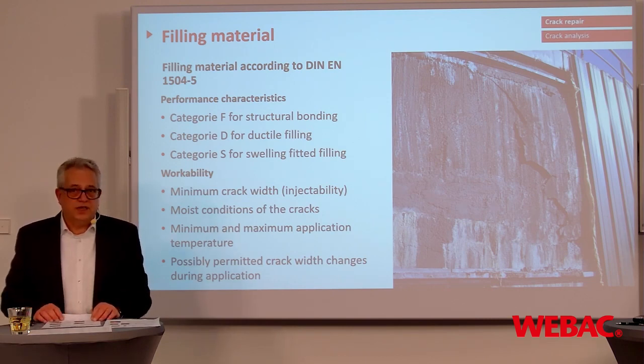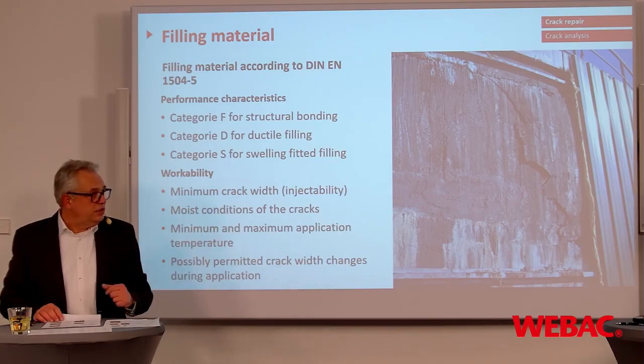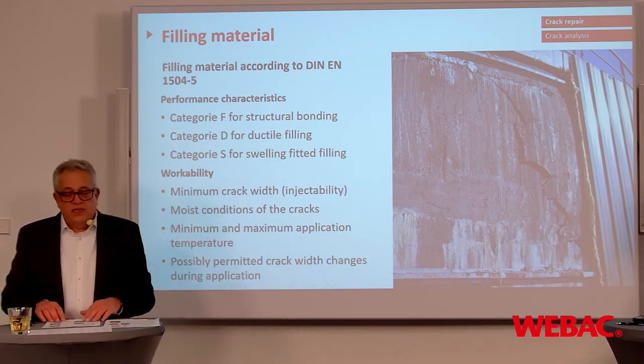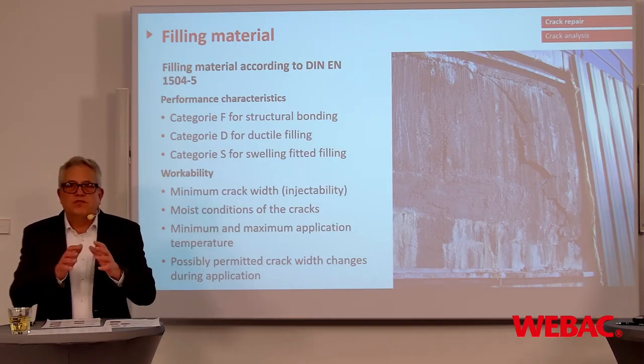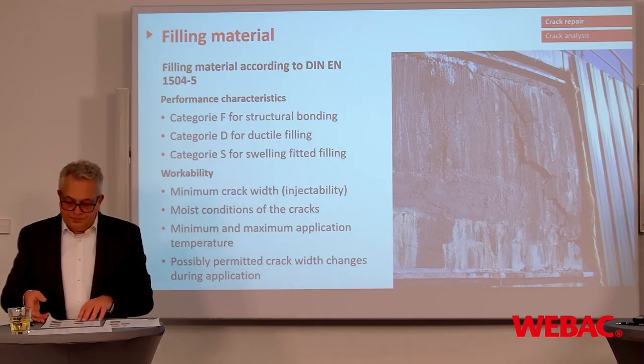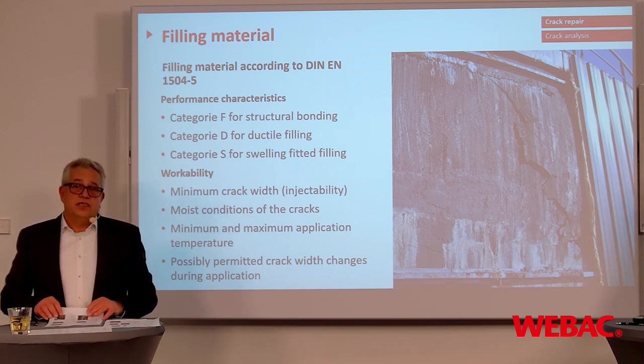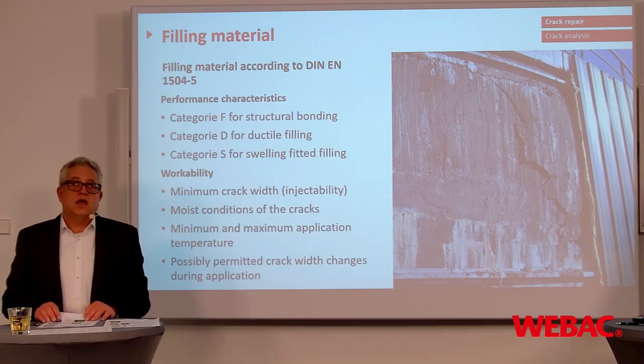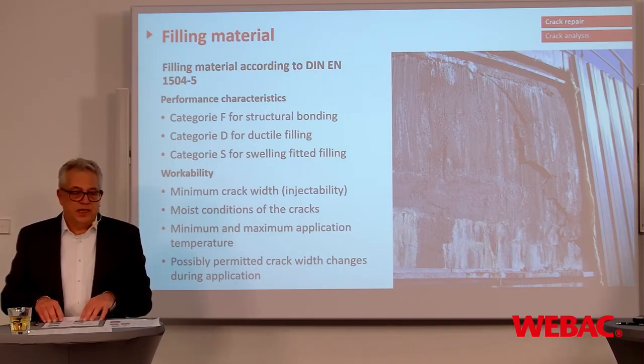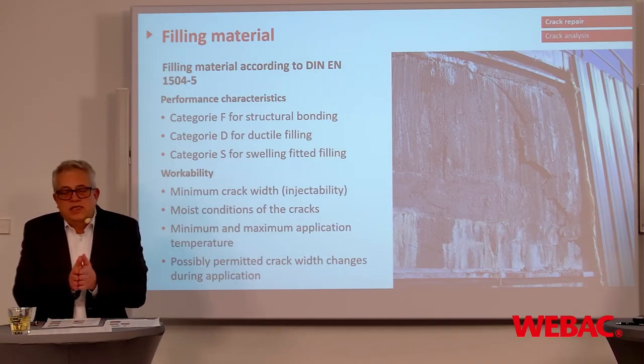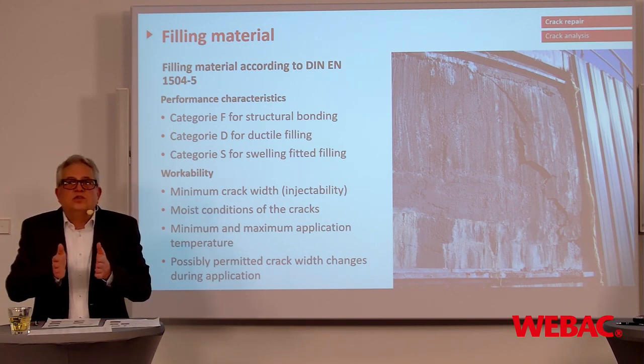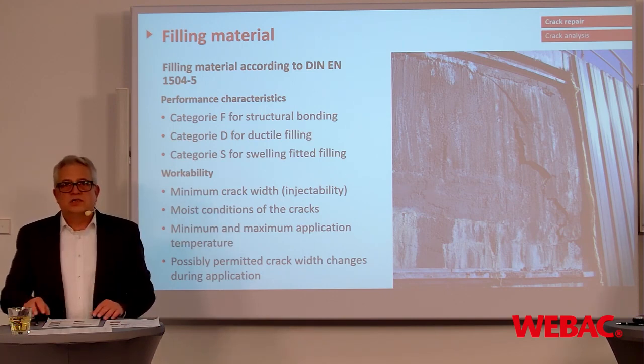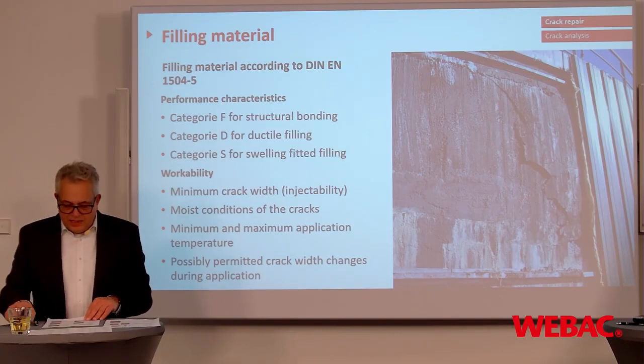Then the ductile filling of the crack. You will come later to the point of the material. This material is a little bit more flexible and can take some movements. And last but not least, category S. There we are talking about acrylic gels, mostly for swelling filling, meaning the material swells a little bit, and due to the swelling pressure the crack gets sealed.